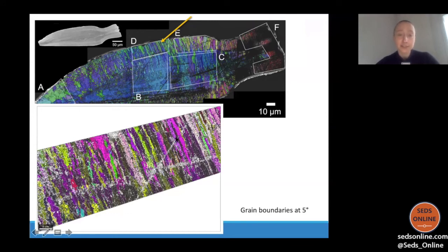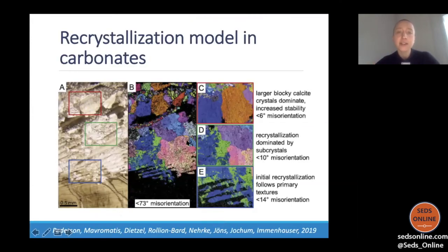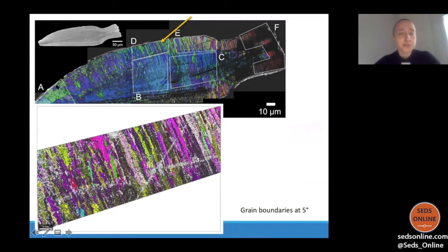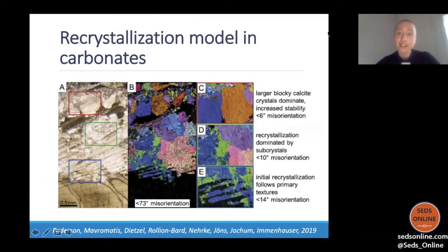And this is what I'm showing here. This is a close-up of this area here. So you can see that any place that didn't have enough signal or had some mistake in the measurement will be resolved as a different grain. There are some smoothing algorithms, but basically, maybe before I get to this, I want to also highlight these areas in the front and in the center that have larger grains. And we don't know if these larger grains are larger because the organism secretes larger grains, or because of diagenesis. And this is where I wanted to mention Chelsea's work, because it has really been a source of information for me on how to approach this. The problem is that this is, again, carbonates.